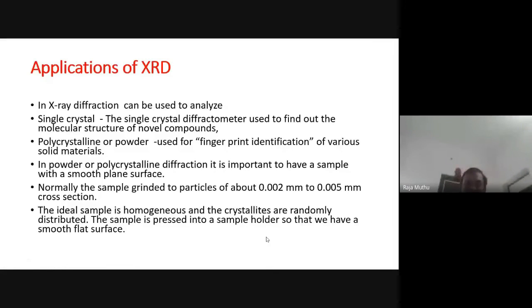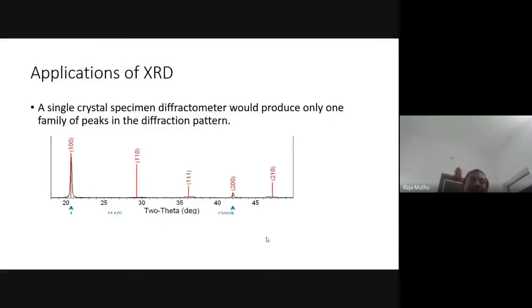It is supposed to be homogeneous, but the distribution is supposed to be random, so we can get a uniform diffraction pattern. All the crystallites are available for all inclinations so that you can get a uniform spectrum. We already discussed that a single crystal specimen in a diffractometer produces only one family of peaks in the diffraction pattern.